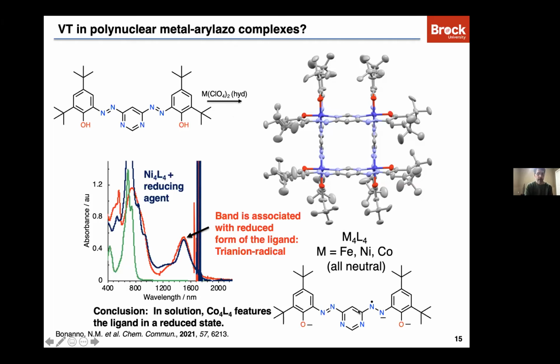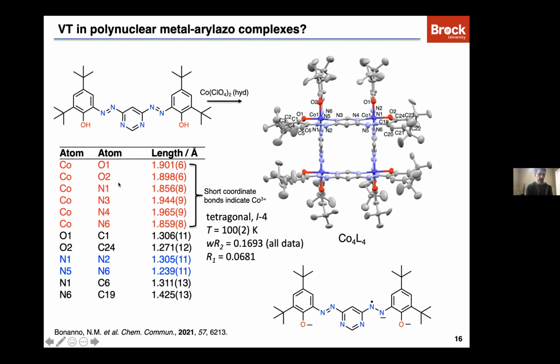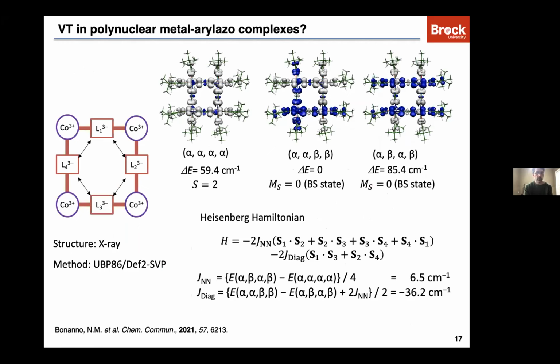So we have a coordinated trianion radical, and cobalt is in the +3 oxidation state. So this is confirmed by the X-ray result. You look at the coordinate bond distances, they're very, very short, indicative of cobalt-3. The ligand bond distances are again unusual. We have one long NN bond, one shorter NN bond, again consistent with this sort of valence bond representation of the ligand. Now, again, the group at OCU has carried out lots of important experiments here on this system, and some DFT calculations have again confirmed that the ligand bears all the spin density in this complex. So we have diamagnetic, low spin, of course, cobalt-3 with ligand trianion radical.